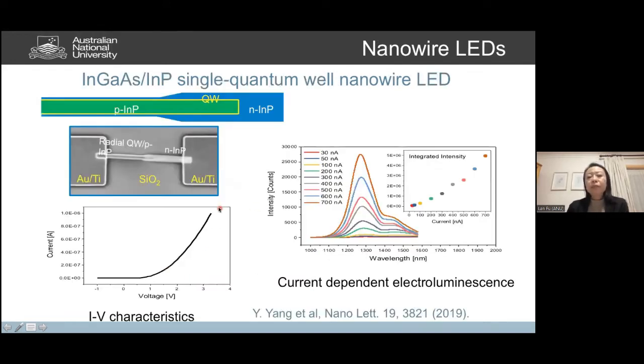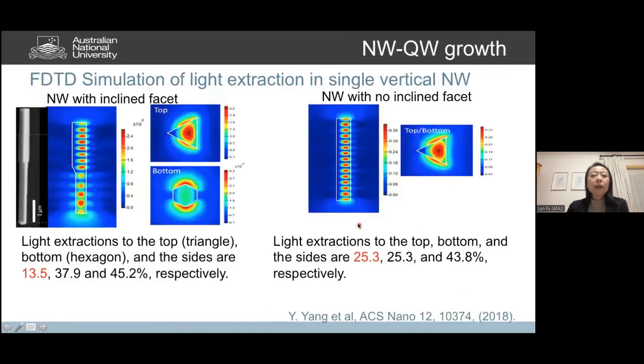And then if we put doping inside the nanowires, as I just mentioned, we can create a radial PIN junction structure, and thereby inject current to get electroluminescence from this nanowire. You can see the IV characteristics from this single nanowire, which show good diode behavior, and the electroluminescence increases with injection of current. Then we want to ask, can we use it to make an array device? How will light extraction be affected by this inclined facet nanowire?